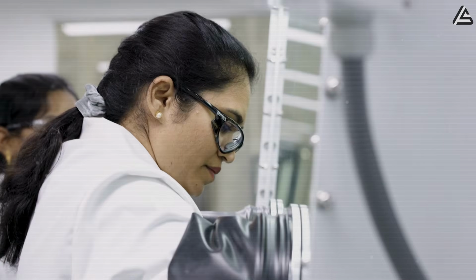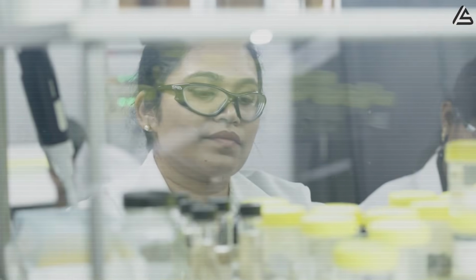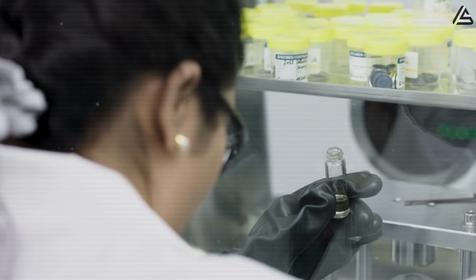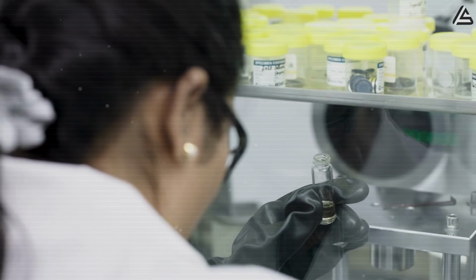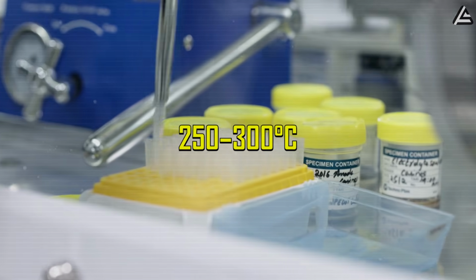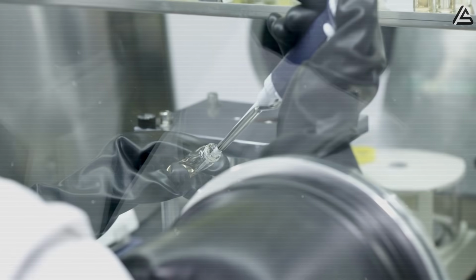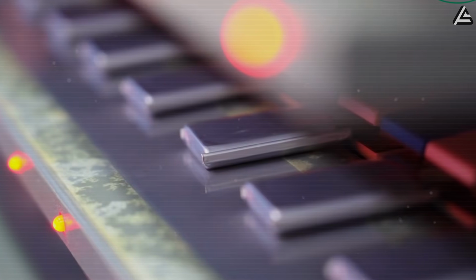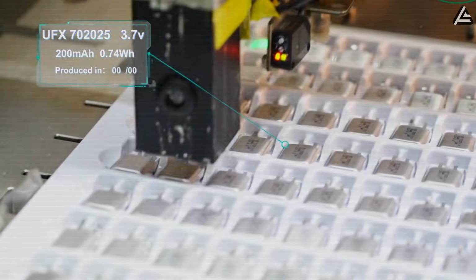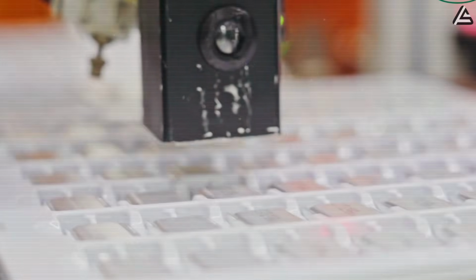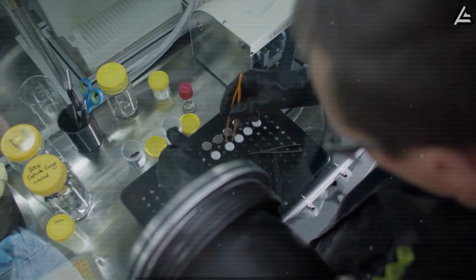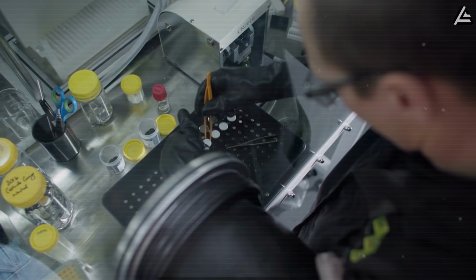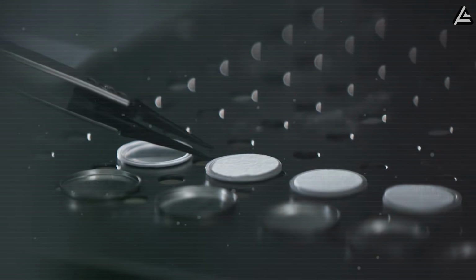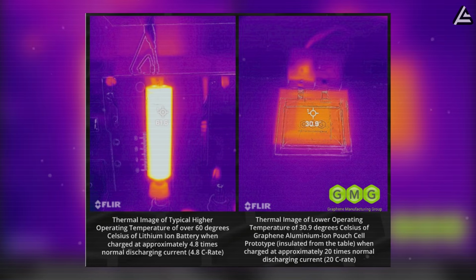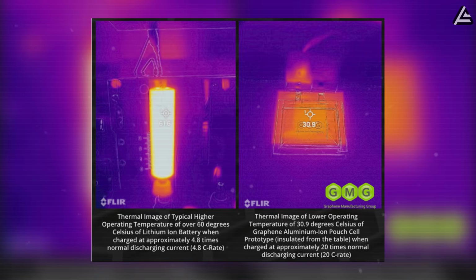Aluminum-ion technology eliminates that chain reaction at its root. Instead of flammable organic solvents, these cells use aqueous or ionic liquid electrolytes that remain thermally stable up to 250 to 300 degrees Celsius, roughly twice the limit of lithium-ion. The aluminum anode doesn't react exothermically when exposed to air or moisture, meaning there's no oxygen release to feed combustion. In short-circuit tests conducted by GMG and the University of Queensland, aluminum-ion prototypes maintained structural integrity at 260 degrees Celsius for over 30 minutes without swelling or venting gas.